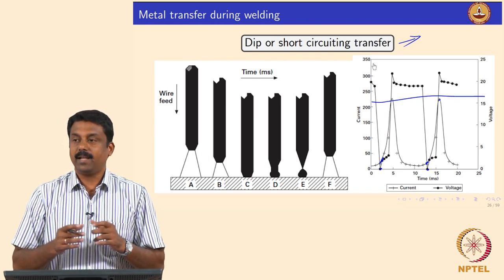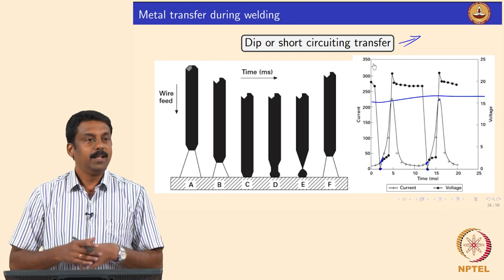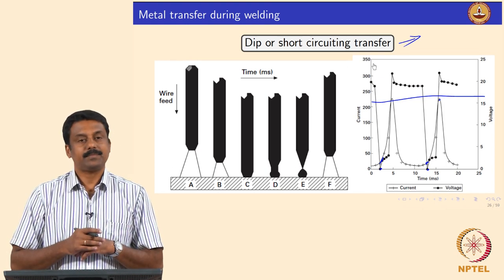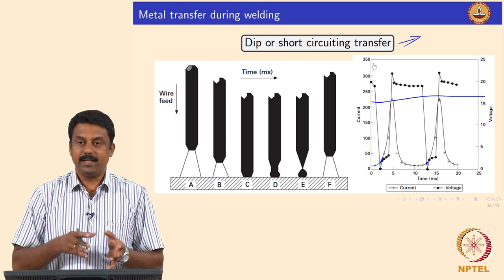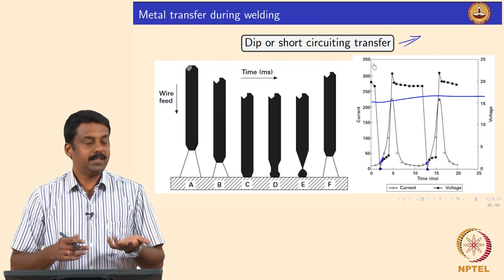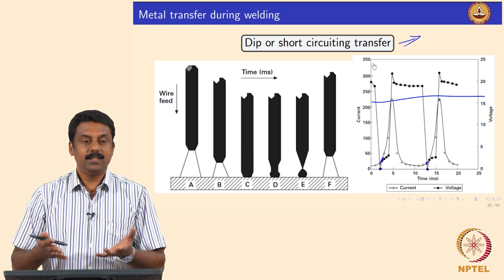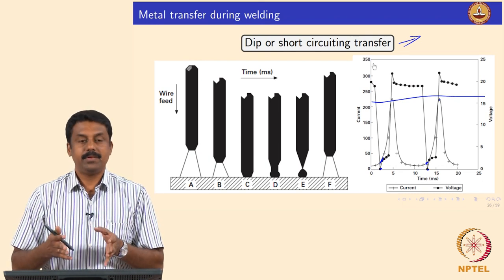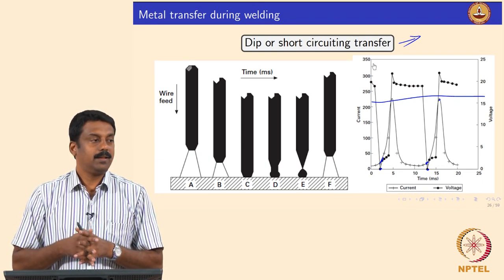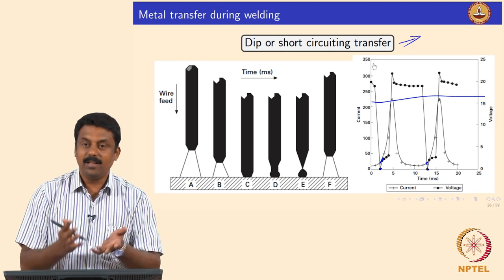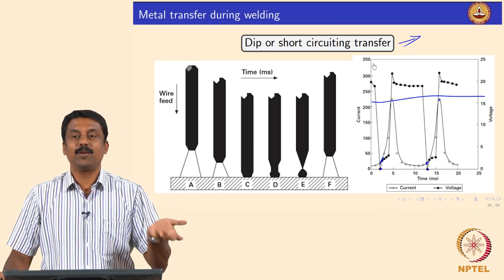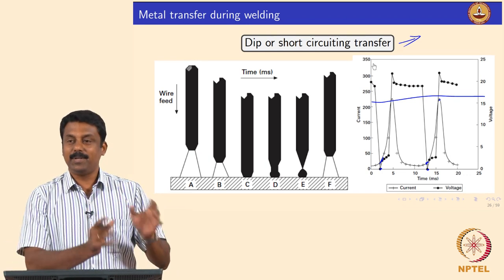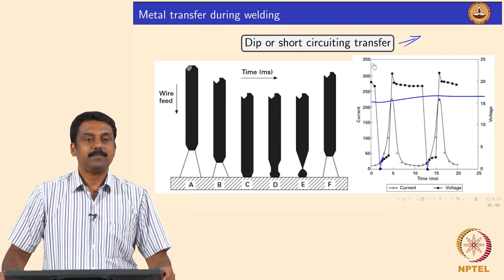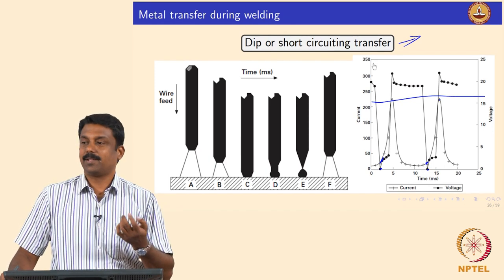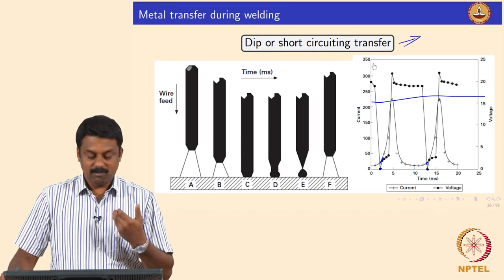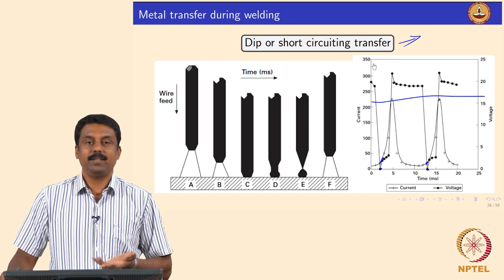So the melting rate has to be calculated for a given diameter wire, for a given composition. Then we can calculate the melting rate. Once you know the melting rate, and we know for a given arc length when short circuiting is established, right? It is clear. And these are all possible because of the microprocessor controlled power sources. The power source has a computer inside, a brain inside, okay. So all the programs are already preloaded by establishing the entire process.